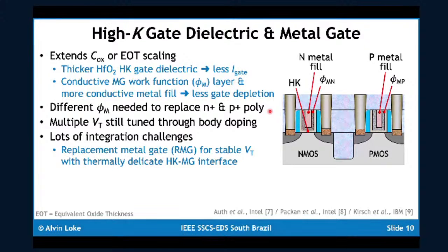One of the key problems with HighK metal gate is that the metal gate to the HighK interface is thermally unstable, which means that subjected to the high temperature source drain anneal typically used to activate dopants, you can get significant shifts in VT that essentially render your transistors non-functional.